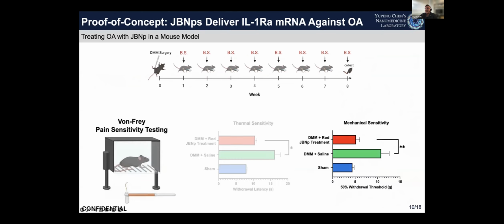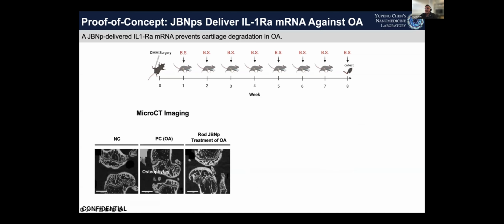Then on von Frey testing, the treatment group mice noticed the stimuli at a higher threshold than the non-treated mice, which was again very, very similar to the healthy control group. This also tells us that the mice in the treatment group were not experiencing pain from cartilage degradation and likely were not experiencing the progression of osteoarthritis. So after collection of their knee joints at the end of the study, we first conducted micro-CT, where we saw that the untreated mice with osteoarthritis had significant osteophyte development, which is a key indicator of osteoarthritis progression. But the mice treated with JBNP demonstrated no osteophyte formation at all, lacking any signs of progressive osteoarthritis.